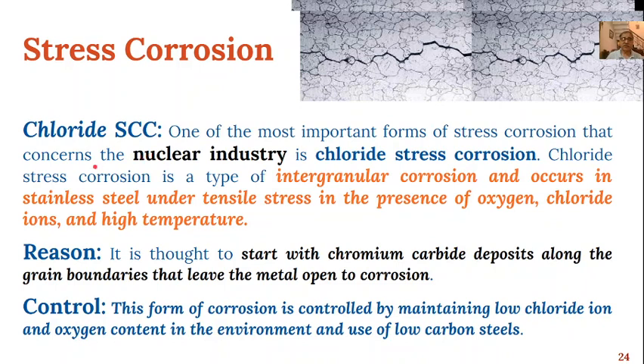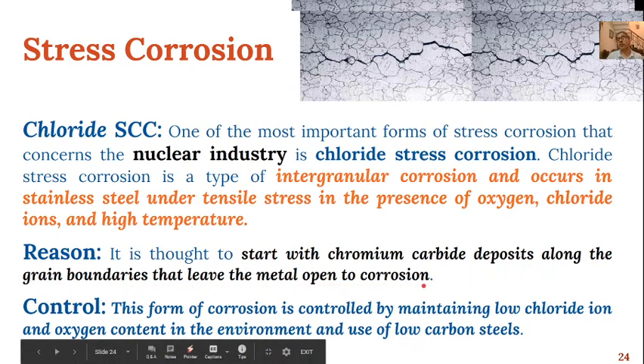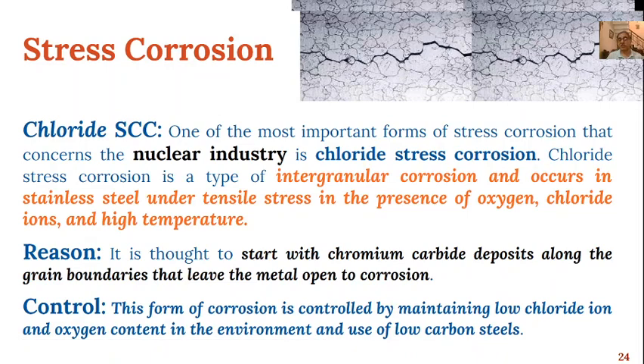And then stress corrosion can be of many types. One is chloride stress corrosion. This is the most important form of stress corrosion, and generally this is seen in the nuclear industry. Here what happens is intergranular corrosion occurs in stainless steel under tensile stress in the presence of oxygen, chloride ions and high temperature. So the reason is the chromium carbide deposits along the grain boundaries that leave the metal open to corrosion, and this can be controlled by maintaining a low chloride ion and oxygen content in the environment, and the use of low carbon steels. So this kind of stress corrosion can be avoided.